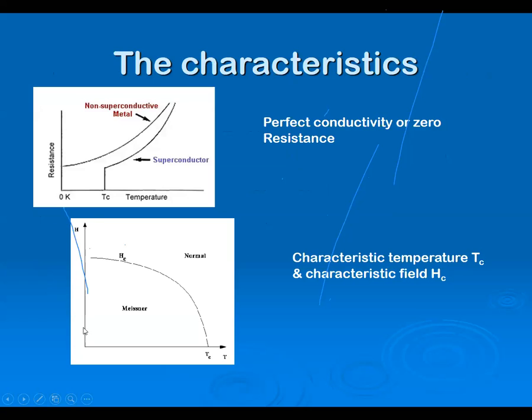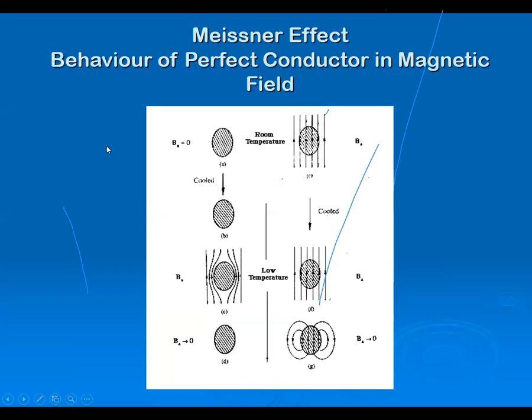You can basically show this if you plot field versus temperature. Above this critical temperature, it is normal, and as we reduce the temperature, it goes to this critical field, above which again it will go to a normal state. Okay, and if we measure the resistance as a function of temperature, for a metal it goes down in this behavior, whereas for a superconductor, it drops at the TC. So this was your Meissner effect, which is pictorially represented in this form.